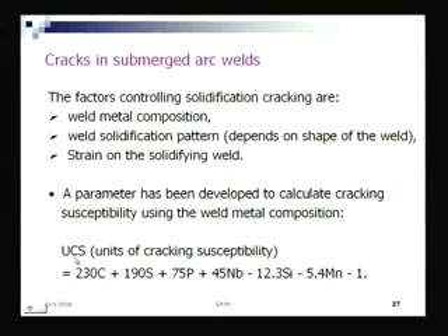So a parameter referred to as UCS, units of cracking susceptibility, has been developed statistically. It is dependent on carbon, sulfur, phosphorus, niobium, silicon, and manganese contents.